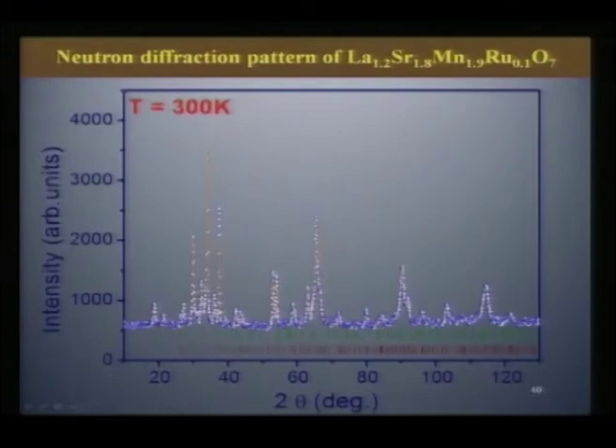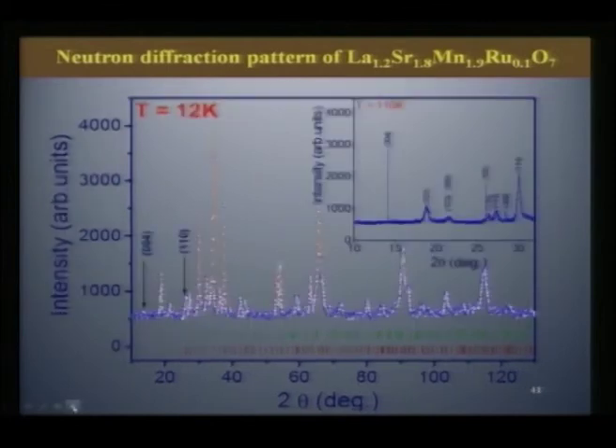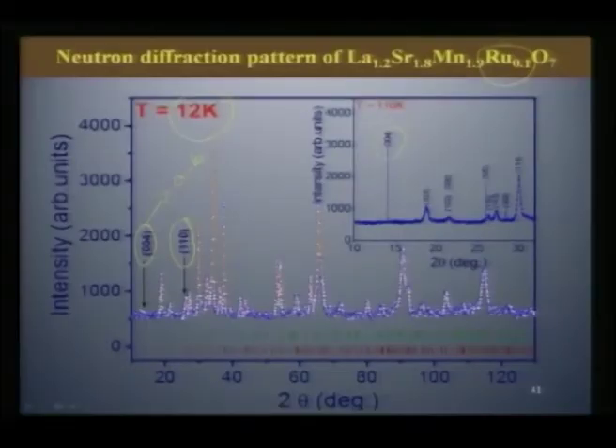This is the neutron diffraction profile at 300 K, but let me take you to the low temperature neutron diffraction profile, where you clearly see that in the case of the ruthenium substituted compound, this 004 neutron reflection or magnetic reflection is absent, whereas this 110 is actually increasing. What is true about that? 004 is absent, which is actually representing the AB plane orientation. Spins aligned in the AB plane will have a characteristic 004 reflection.